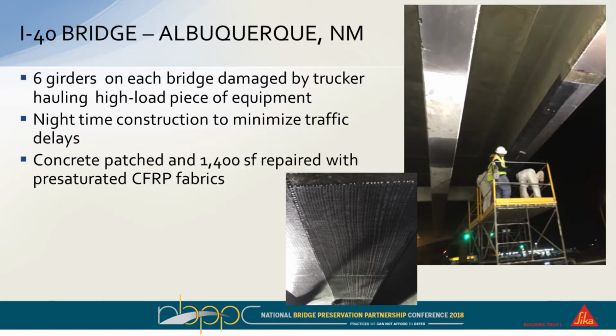And then a similar application on the I-40 bridge in Albuquerque, again, a high load piece of equipment struck the underside of the girder. In total, 6 girders were actually affected by this one. Here, the New Mexico DOT wanted all this done as nighttime construction, again, to minimize delays. And again, about 1,400 square feet of concrete was patched and then strengthened with the pre-saturated FRP materials.